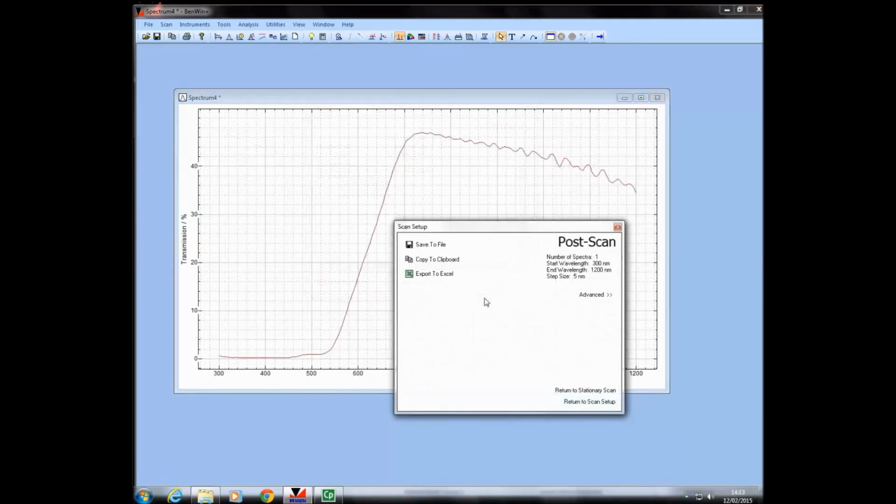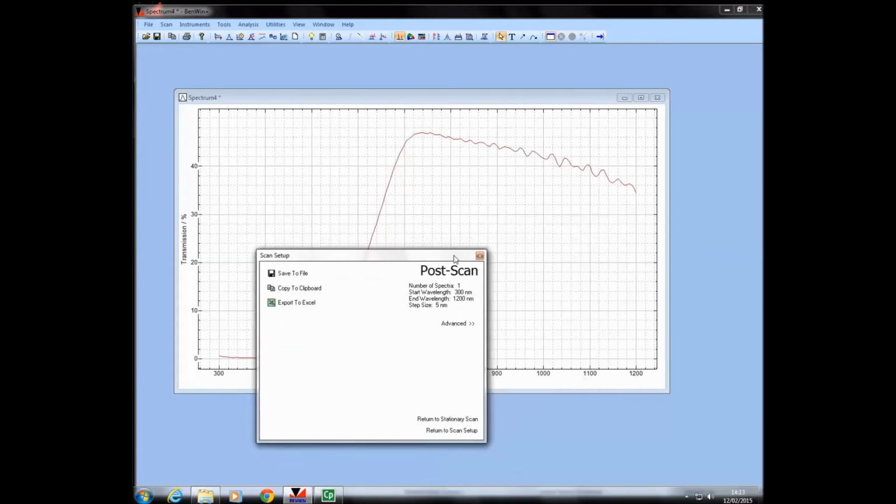And we have the measurement of the spectral transmittance of this particular sample, showing interesting interference effects at the longer wavelengths, no doubt due to the thin films deposited on the sample. We can use this with the measurement of the reflectance of the device to modify the external quantum efficiency measurement to obtain the internal quantum efficiency.